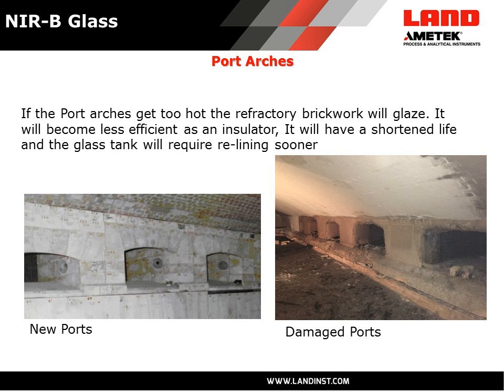So again, new ports. This is a cross-fired tank. New ports, very well defined, nice clean edges, good refractory materials, never been used yet. Here's a tank that has just been brought down for a reline. And in this tank, you can see the damage that's occurred around the ports and how the refractory has melted and in some cases cracked away from the port arches and fallen.